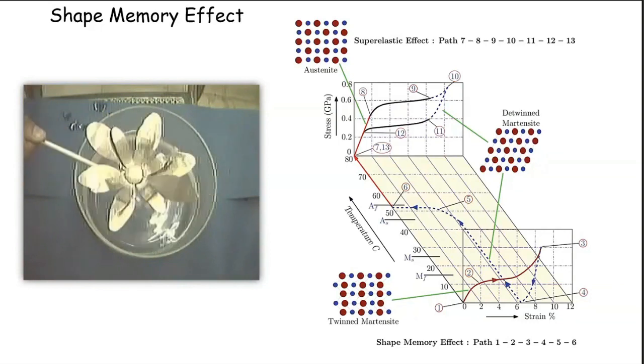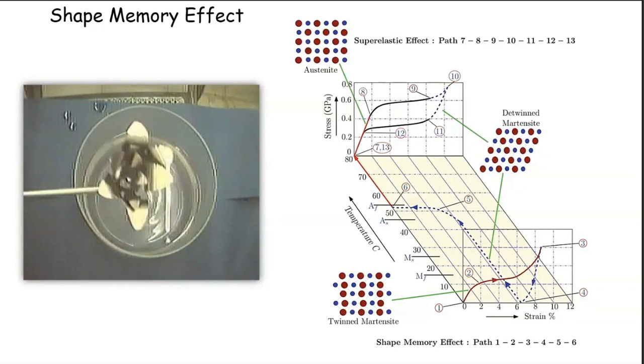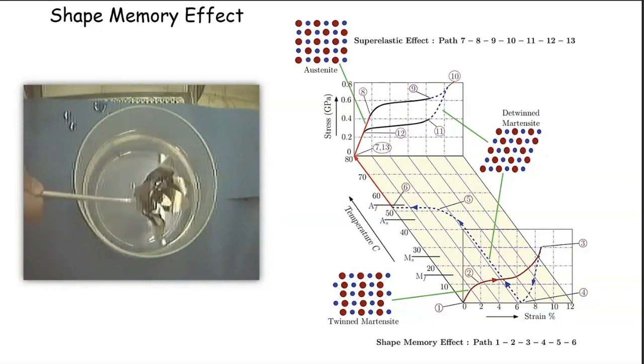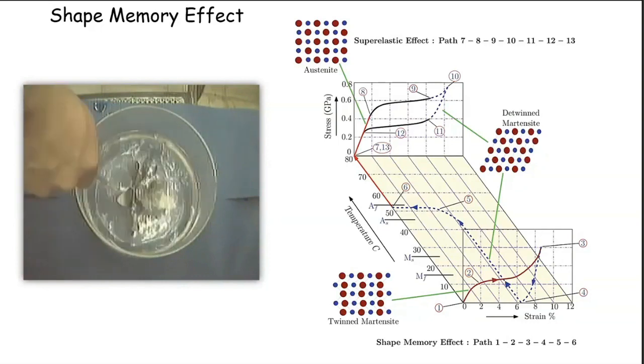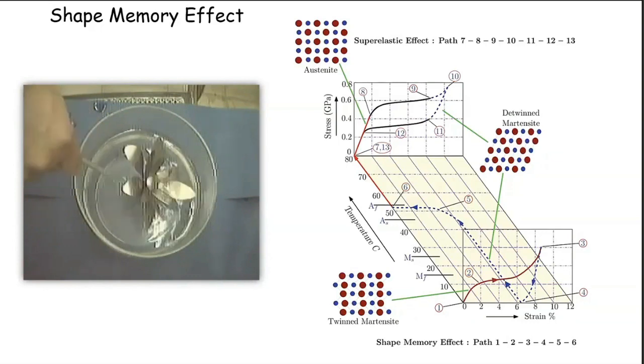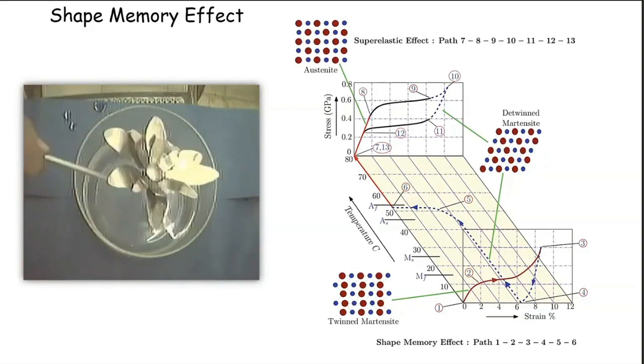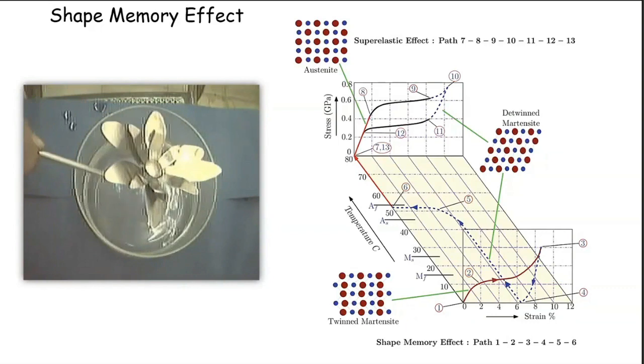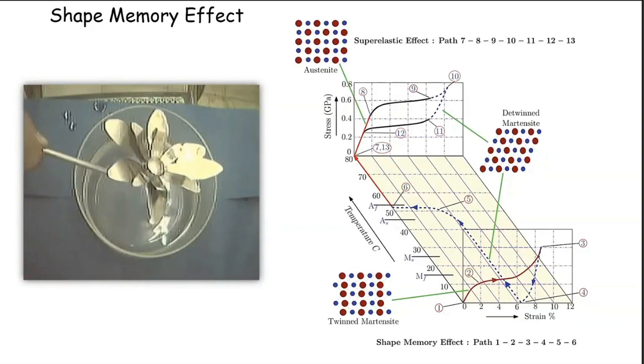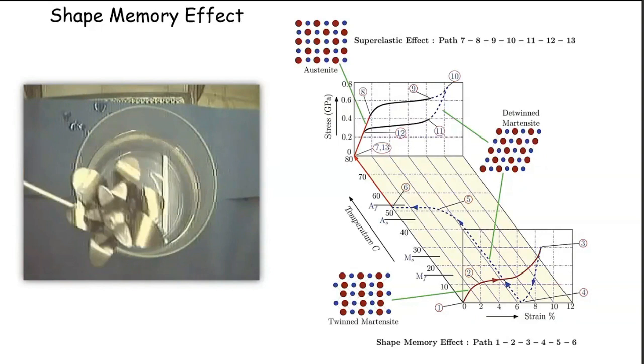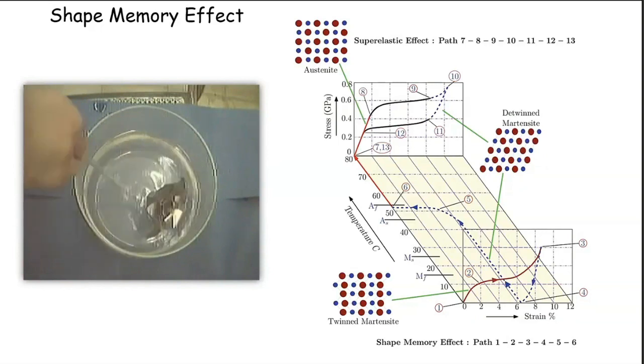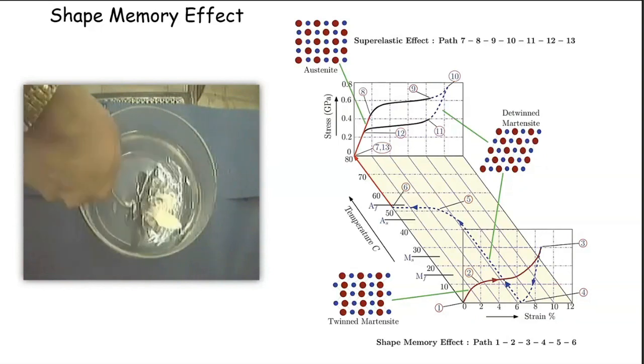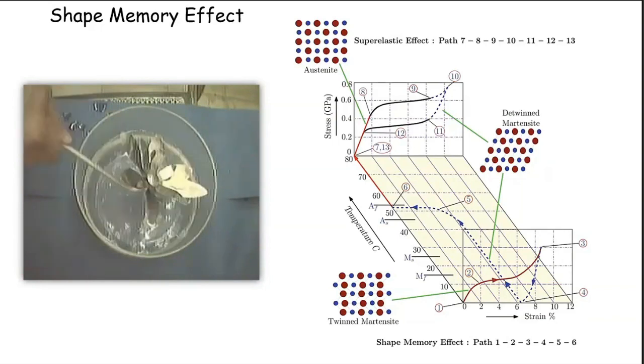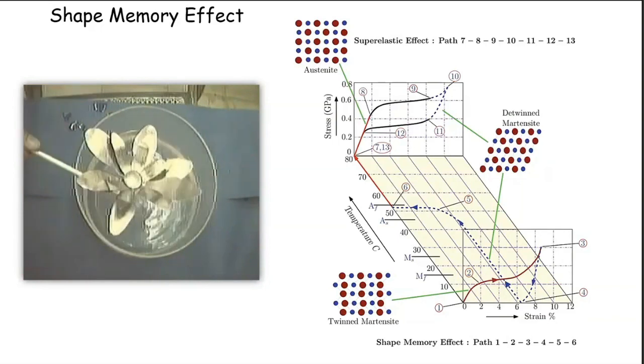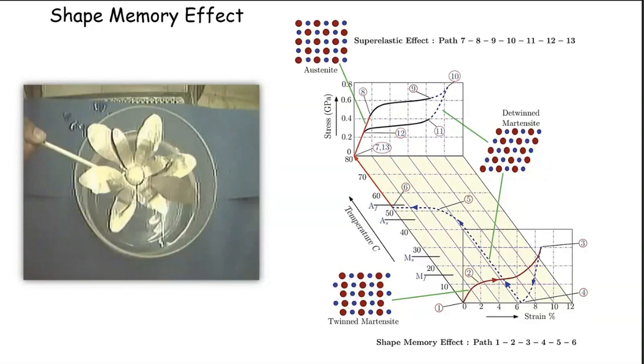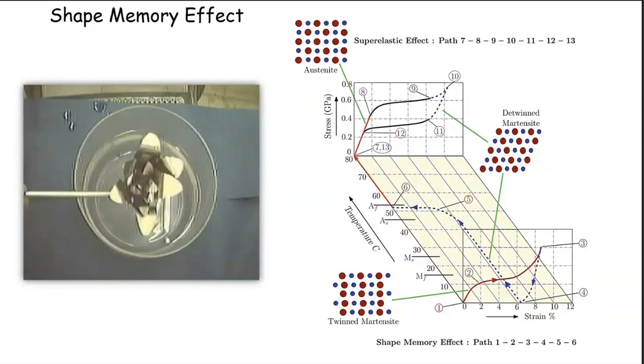So one of the ideas they had, a simple thing that appeals to all, was to make a shape memory flower. What this is, is that you have taken nickel titanium, arc melted it. This one is equiatomic, which means 50-50 atom percent, so roughly the weight percent will be 45-55. And you hot roll it, and this has been additionally chemically polished, so that's why it's so bright. Some petals have been cut out and stacked into a flower, and it's very soft at room temperature. So when you deform it, you can do so very easily. It's about 100 MPa is the stress that you require to deform it.